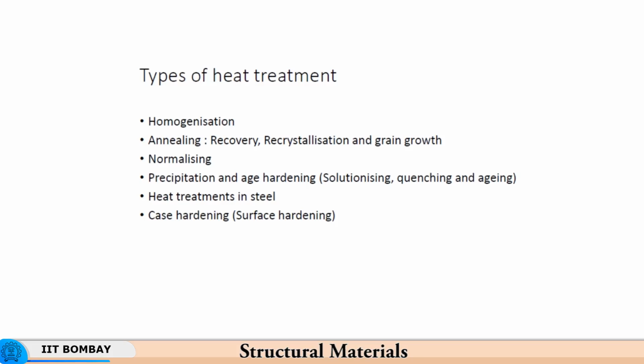So, what we need to do is make the surface hard, because supposing there is a crack at the surface or the root, or some stress concentration taking place, or for some reason there is a crack, then it should not propagate rapidly. If I harden the material throughout, then I am losing in terms of fracture toughness, because once the strength increases, the ductility decreases. When I make the entire bulk of the material strong, I am paying in terms of reduced fracture toughness, reduced ductility.